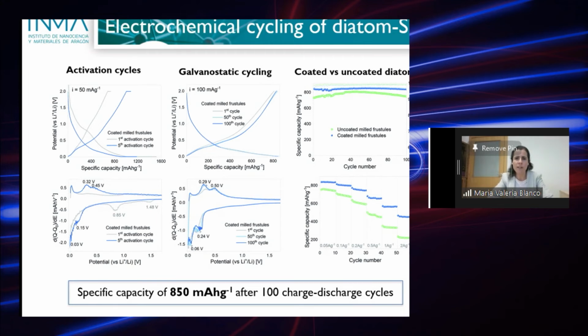So on the right part of the slide, you can see a comparison of the coated versus uncoated diatoms. The green dots represent the uncoated milled diatoms, and you can see that the specific capacity is not quite stable. It increases a bit and then it lowers. Whereas in the case of the coated diatoms, you can see that the capacity is really stable, which means that the coating was very effective.